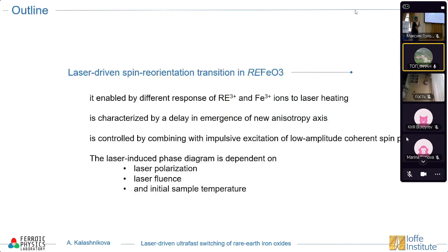So this brings me to the conclusions of this part: in principle, the ultrafast spin orientation transition in rare earth orthoferrites is enabled by ultrafast heating. And what is important is that there is a kind of delay which is required to repopulate the rare earth ions' state. And we can use this delay, and we can combine it with the ultrafast inverse Faraday effect in order to control the way magnetization switches.